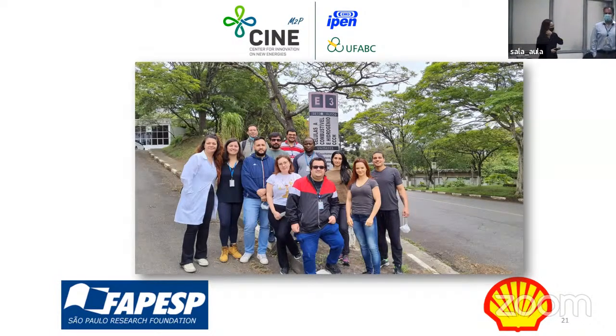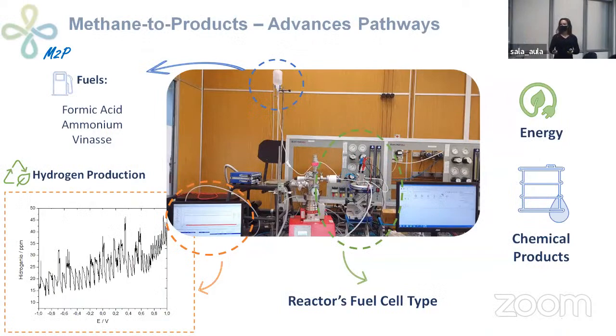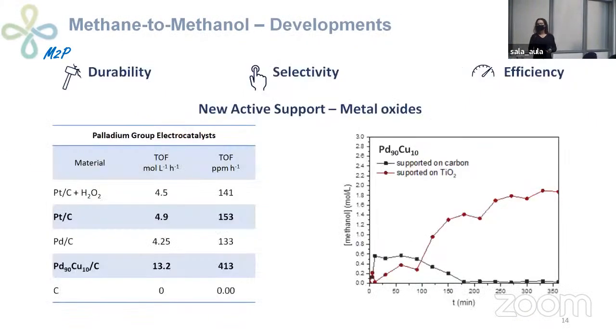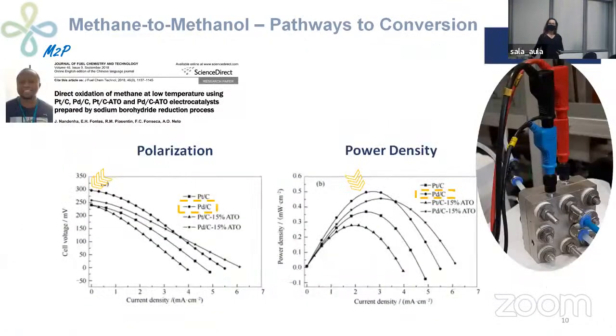Thank you, Priscilla, for this very nice talk. I'm just wondering why the open circuit potential changes when you add palladium to the system. Slide 10, you show that. I think that is 10. Yes, yes. Here we have the high open circuit potential for the palladium. Here we believe there is some synergy between this formation, the oxygen reduction reaction, and the methane activation.